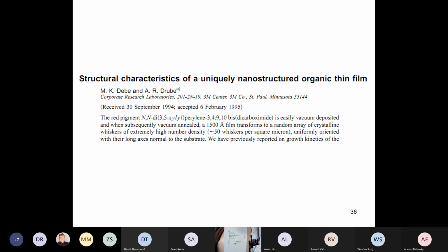And anyway, Mark, in the late 1980s, he discovered this stuff. This red pigment is easily vacuum deposited, and when subsequently vacuum annealed, a 1500 angstrom film transforms into a random array of crystalline whiskers of extremely high number density, 50 whiskers per square micron, uniformly oriented with their long axes normal to the substrate. So in the late 80s, Mark discovered this, and then 3M decided, well, we're not going to tell anybody about this because maybe this is useful for something. So it wasn't until like 6 years later that he published anything on this. And in the meantime, they realized that this could be used as a catalyst support.